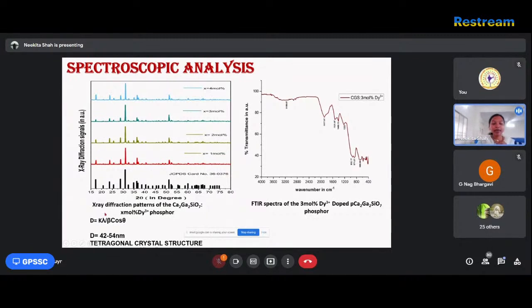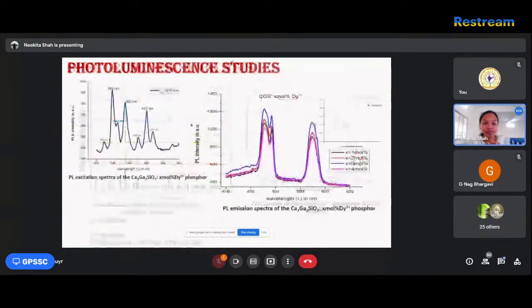The particle and crystalline size of the prepared phosphor were calculated by the Debye-Scherrer formula, where K is the shape factor, lambda is the wavelength of the X-ray, beta is the full width at half maximum, and theta is the diffraction position of the material. The calculated particle size of the phosphor ranges from 42 to 54 nanometers, and the prepared phosphor has a tetragonal crystal structure according to the previous literature.